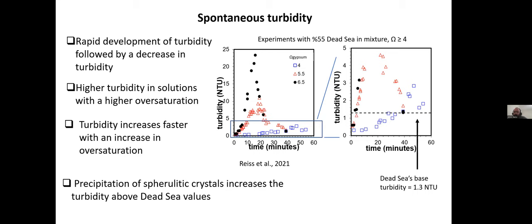So I basically took it as a conservative criterion to increase turbidity, where a person standing outside and looking into the lake would observe increased turbidity. And we could see that within a relatively short time, all the experiments passed this base of the Dead Sea turbidity. We also see that in higher oversaturation, we reach higher values of turbidity, and we see them faster. So basically, the spherulitic morphology crystals can pass the turbidity of the base Dead Sea and potentially cause a whitening